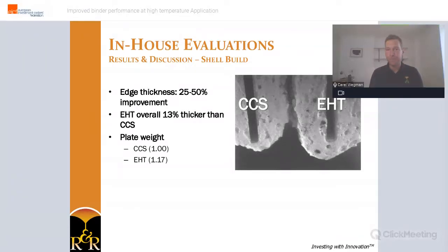So, shell build. For casting gas turbine blades and vanes, the shell thickness is of course very important, not only on flat surfaces, but more critically around the thin and sharp trailing edge. Obviously, it's harder to retain slurry and stucco on a sharp edge than on a surface. And as a result, the trailing edge of a vane becomes the weakest point and is most likely to crack at dewax. Foundries often build shells with extra coats to build up sufficient thickness around the sharp corner, but the extra coats typically provide little benefit to the rest of the shell.